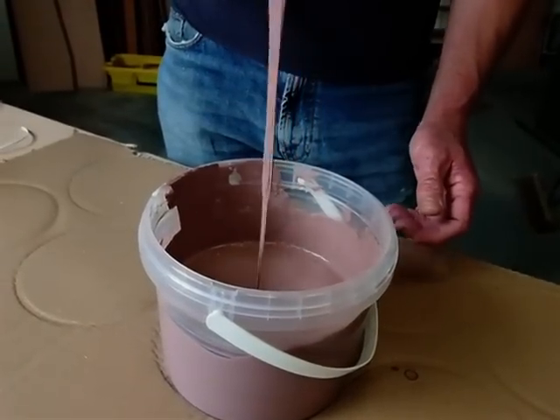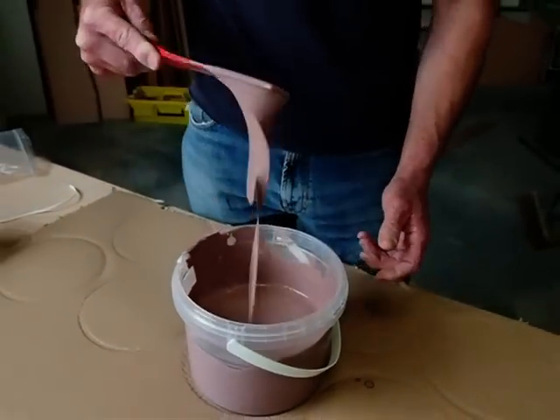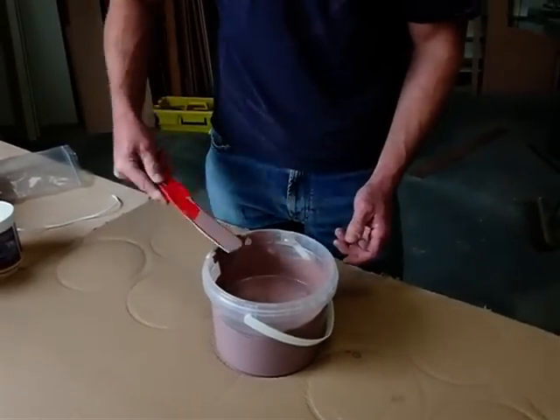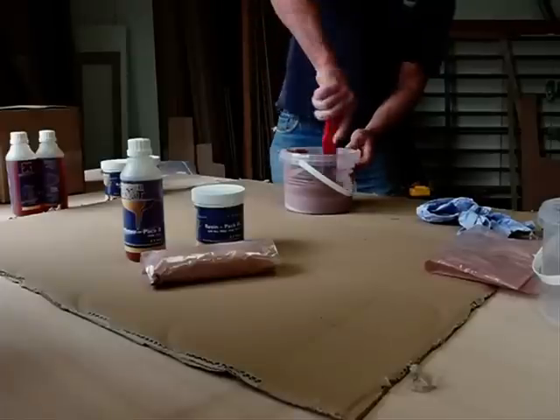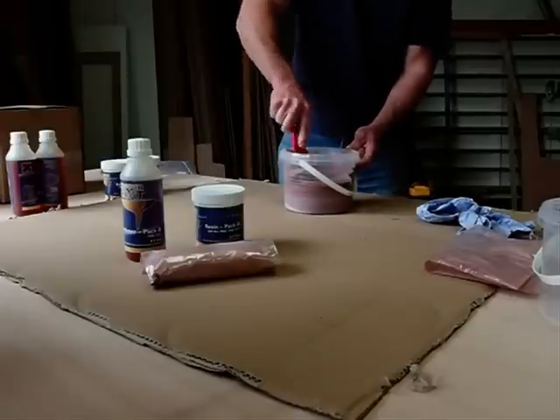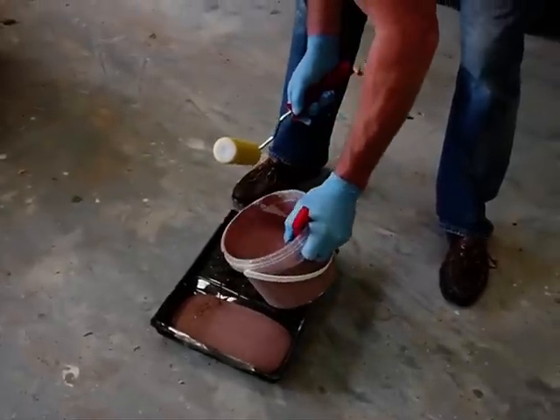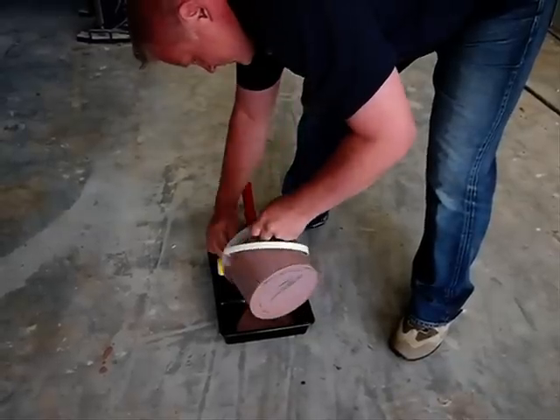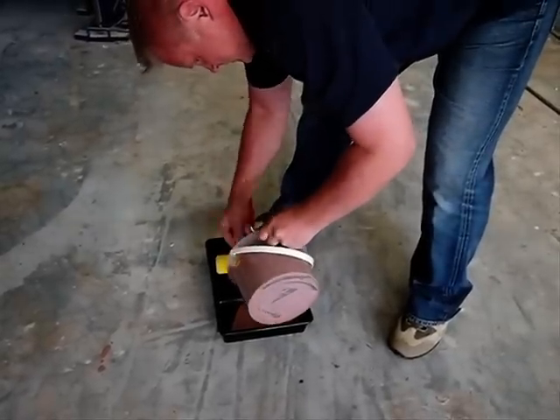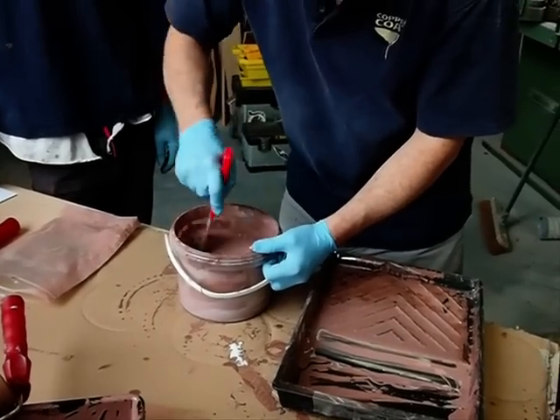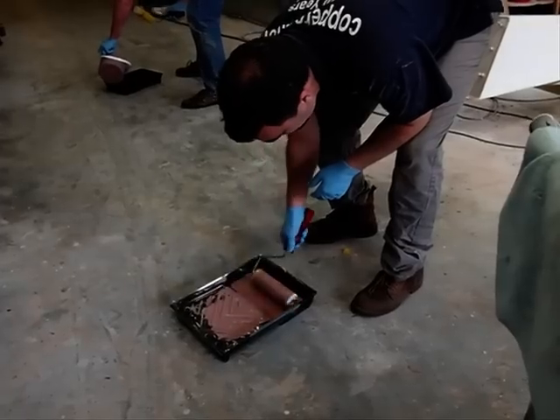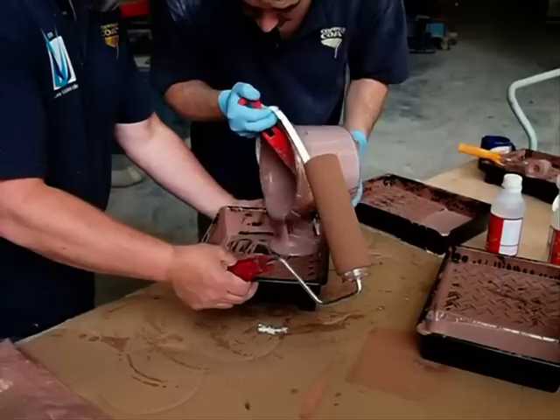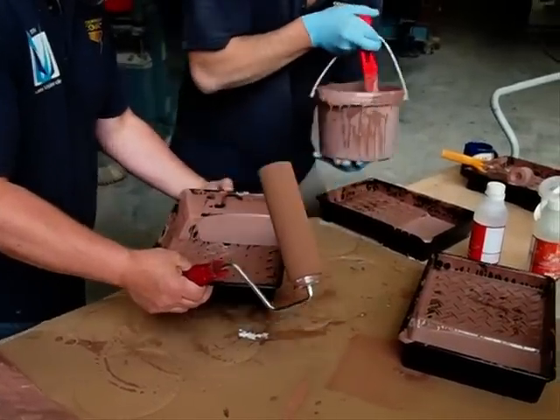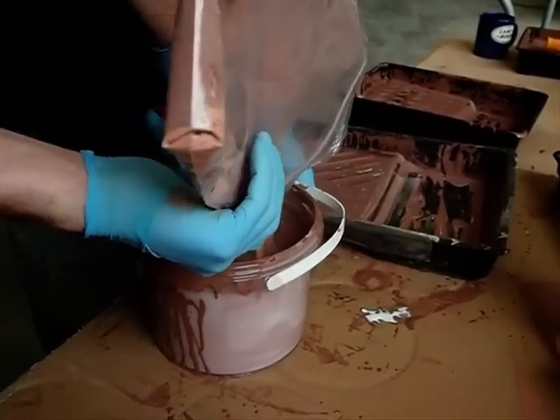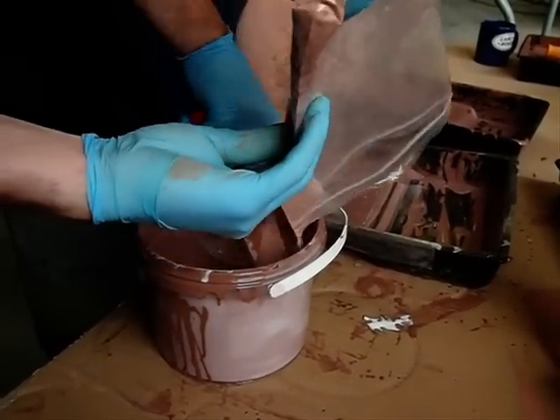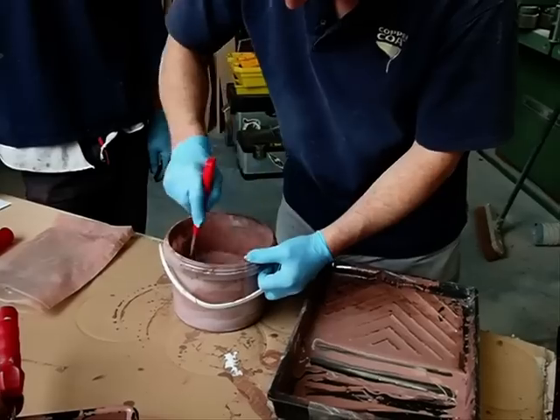During the pot life of this 1 litre mix, the copper may well settle to the bottom of the bucket. Consequently, always give a good mix when you return to the bucket to refill your roller tray. Similarly, do not overfill the roller tray, as the copper will settle in the sump. It's better to use several small amounts, returning regularly to the mixing bucket for a freshly stirred product. Never mix more product than can readily be used within the time available. We recommend that only 1 litre be mixed at a time.